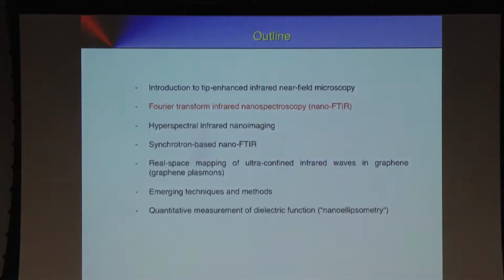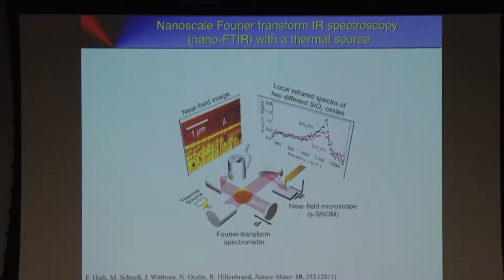All right, so up to now I've talked about imaging, so I want to point out these were single wavelength images done with monochromatic lasers, so either gas lasers or quantum cascade lasers. Now the next logical step, of course, is to do spectroscopy, and our idea was, well, the most simple broadband source is a thermal source, and it was actually Florian Huth, now working at Neaspec, and is the head of research and development there. Well, he came up with buying this €100 coil that is heated up to 1000 Kelvin. And then we project this thermal source onto the AFM tip, and we collect the backscattered light, using a Michelson interferometer as a Fourier transform spectrometer.